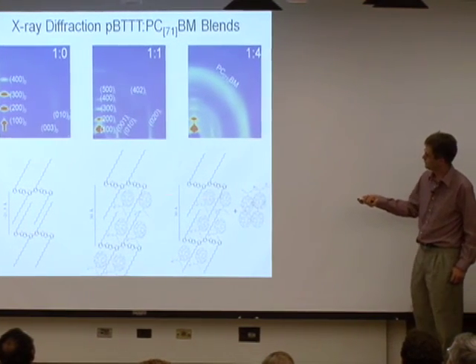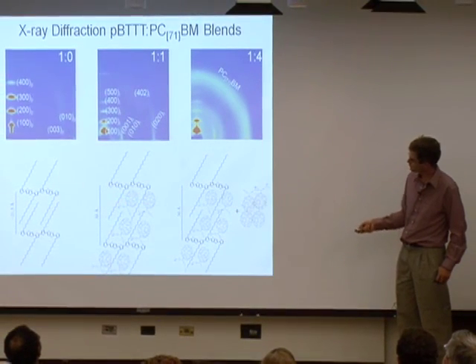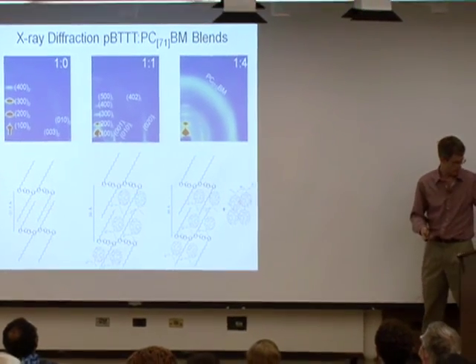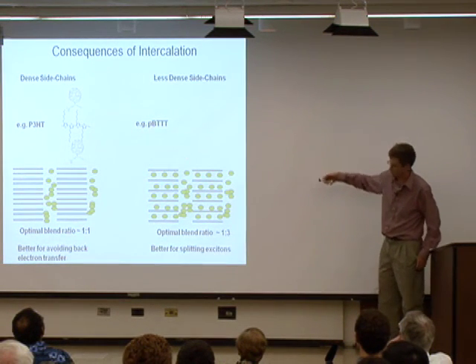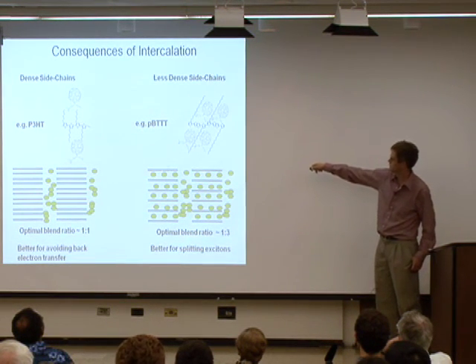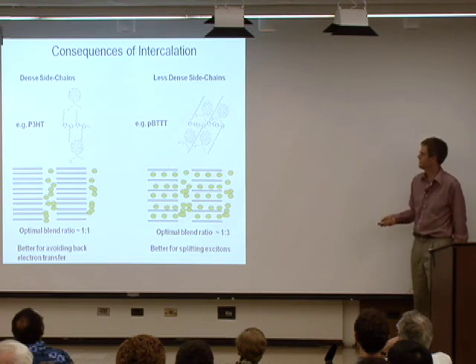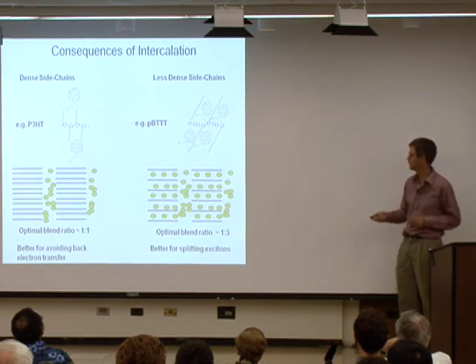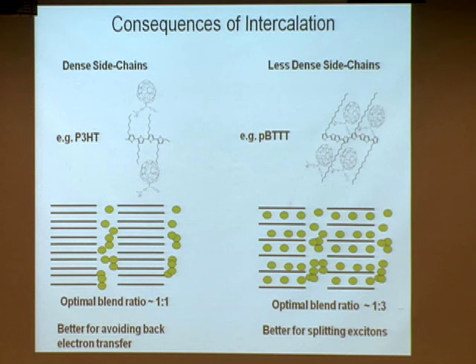And so it turns out that when the molecules go in there, that is, of course, really good for exciton splitting, because the polymer chains are right next to the fullerenes. On the other hand, it's not so good for separating electrons and holes, because as the electrons work their way out of there, they're right next to the holes. And so the recombination, or you could think of it as the backward electron transfer, can be kind of fast. So there's both an advantage and a disadvantage of having the molecules mixed right at the molecular level.